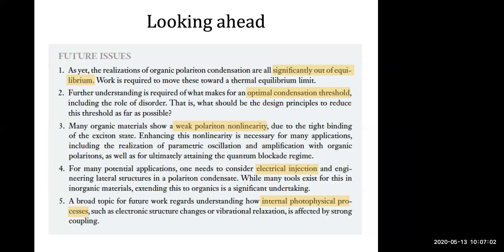Yeah, that's a good question. To my knowledge, no one has studied these organic polariton condensates under circular polarization pumping. One reason for that, okay, I should take a step back. One thing to consider first is how these systems are being pumped. In most of our experiments, we pump beyond the mirror stop band, and normally there's a minimum in the reflectivity of the mirror only for one of the polarizations. So if we come in with circular polarization, in the end only one linear component of that polarization will be exciting the molecules. So under a typical configuration, we wouldn't see an effect.